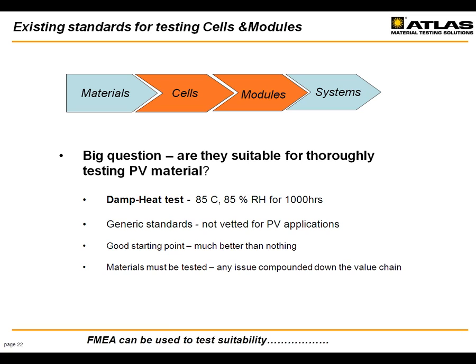And it is well understood that light is a very critical part of testing any material that is going to be subjected to sunlight, especially in such a harsh and direct way and for such a long time. Also, the conditions of 85°C and 85% relative humidity don't exist and cannot exist together anywhere in the world. So there is a question about the meaning of the damp heat test.